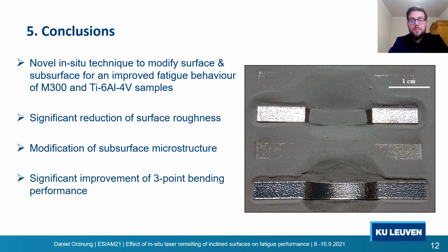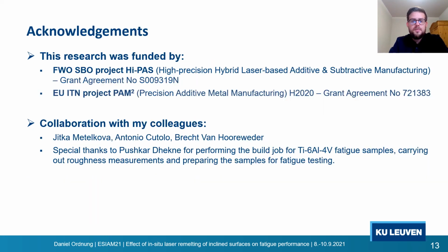In the fatigue 3-point bending tests, the samples which were remelted showed a significant improvement. At the same stress level, they withstood it several cycles longer, while they failed at much higher stress levels. For future work, it will be interesting to investigate more what impact the modified subsurface microstructure has on the crack initiation and the fatigue performance. Also, it will be interesting to upscale the technique for industrial applications.